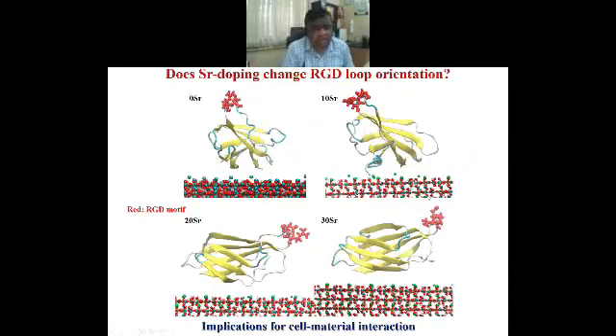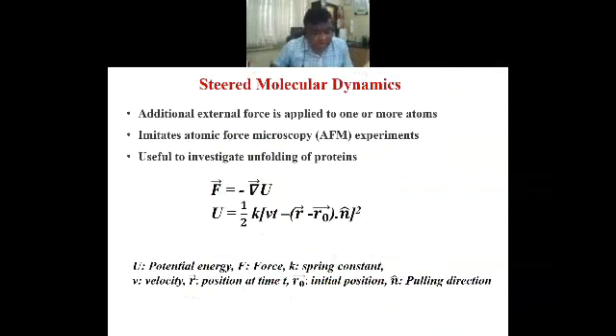So then the next question that we addressed was whether strontium doping will influence the way the RGD loop is oriented. The RGD loop is very important because it should be oriented towards the solvent side, not the material side. Because if the RGD loop is exposed to the solvent side, then only will they favor the interactions with the cell surface receptors. Having said that, what you can notice here is that irrespective of the dopant content, the RGD loop is always exposed to the solvent side, and that is very good to enhance the cell-material interaction.